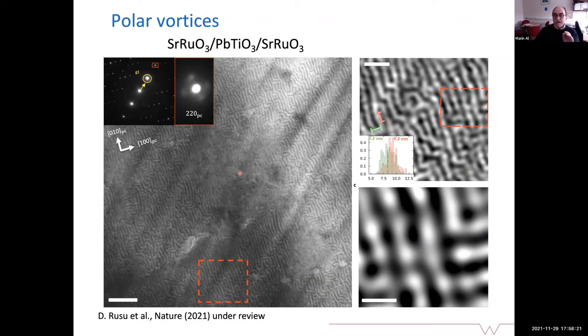And then we see that we do not have only one periodicity, we have two periodicities. This diffraction is in reciprocal space, like a natural Fourier transformation. If you look carefully, you see a kind of necklace, with beads on this necklace. If you zoom in, you see them better. If you do a little image filtering just to clean the noise, these occur absolutely great on each line here, which is a domain. So the conclusion is that this domain actually has a second periodicity.